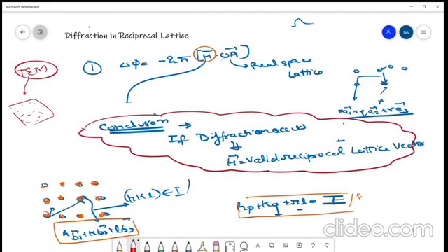If diffraction occurs, that means delta phi is 2n pi, and that means HP plus KQ plus RL is actually an integer. PQR was an integer to begin with. HKL we were not sure about, but with this condition we know now that HKL are integer, and that means this vector HB1 plus KB2 plus LB3 will be a valid reciprocal lattice point.